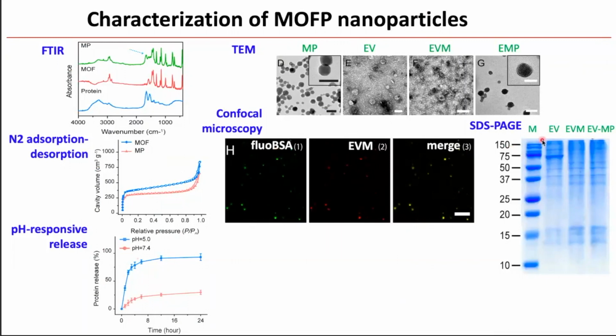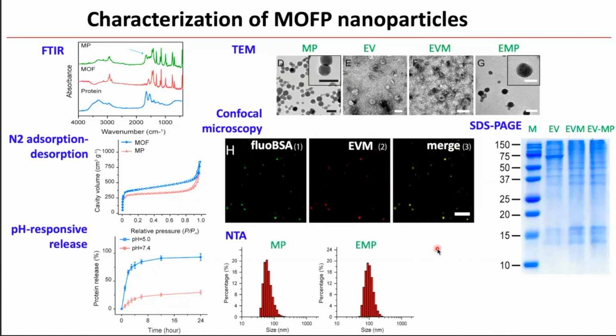And then this slide shows the uniqueness of the EV membrane. In this case, the EV membrane before and after coating on the nanoparticles shows differences compared with the total EV protein. And then, of course, we use nanoparticle analysis to investigate the size of the particles before and after EV enclosure. We also studied the zeta potential, showing that after the membrane enclosure, the surface potential becomes negative, which is consistent with the negativity of the EV membrane.